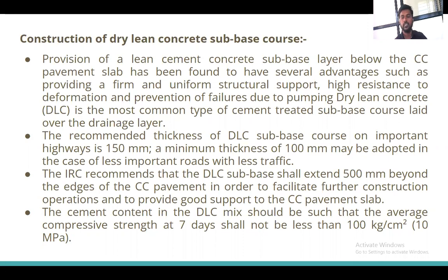IRC recommends the DLC subbase shall extend 500 mm beyond the edges of the cement concrete pavement. Whatever width is desired for the PQC, that is the pavement quality concrete layer, beyond that layer at least 500 mm should be extended by the DLC. This is the recommendation given by the IRC.